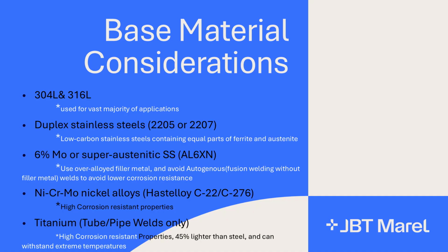And I've done a few of them myself, welding titanium to stainless steel sheets, and it doesn't necessarily weld too much different as far as your duplexes. Your duplexes, to put it into perspective for you guys, even if you're not ever going to weld duplex: as soon as you put down that hood and that light turns on, it looks like somebody threw dirt in your weld puddle. Like, it just looks dirty. You can clean up your base material on both sides, but it just seems dirty.